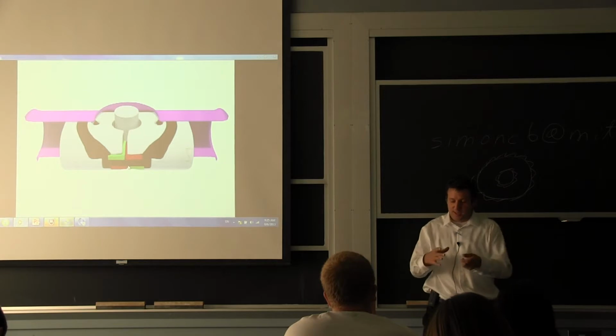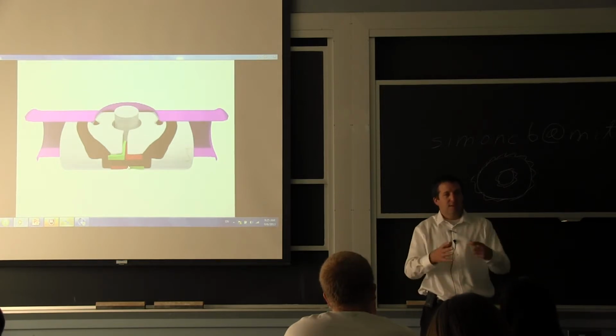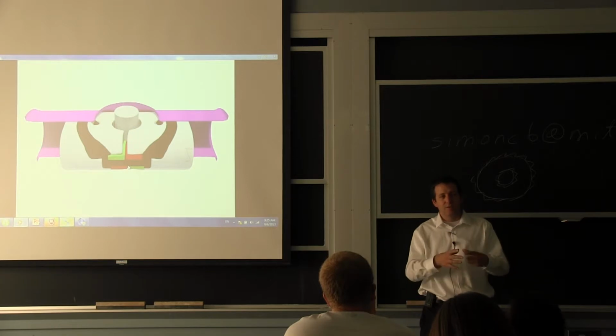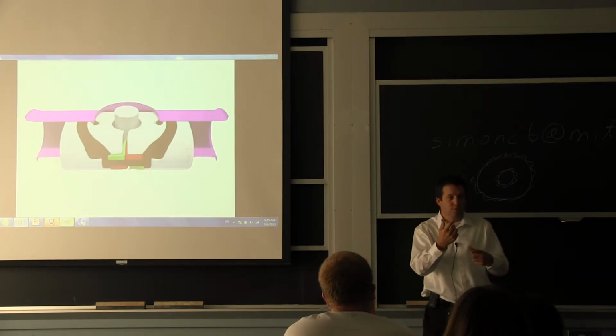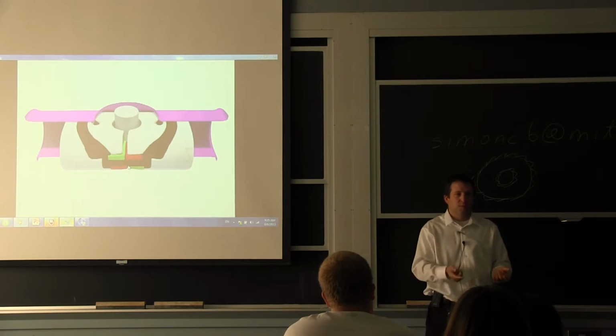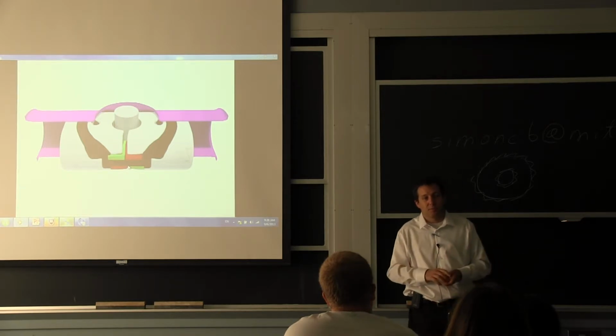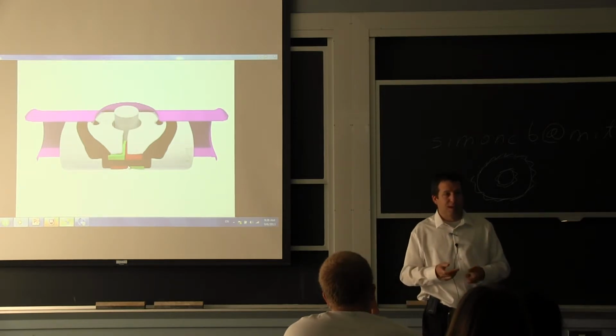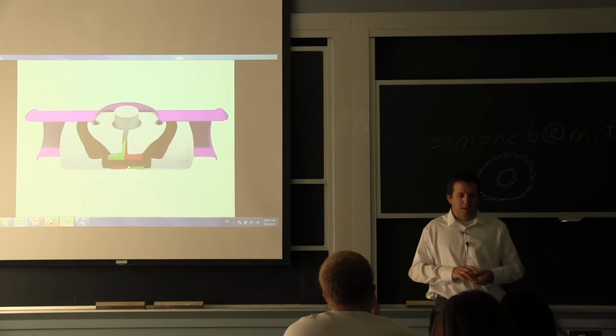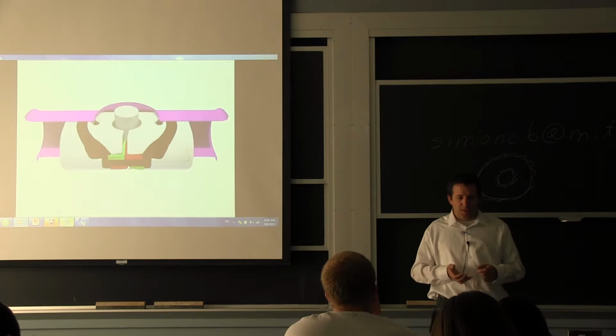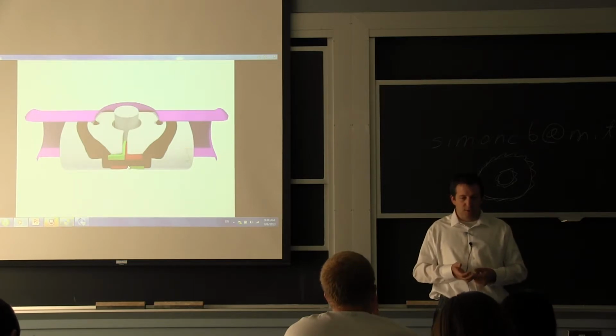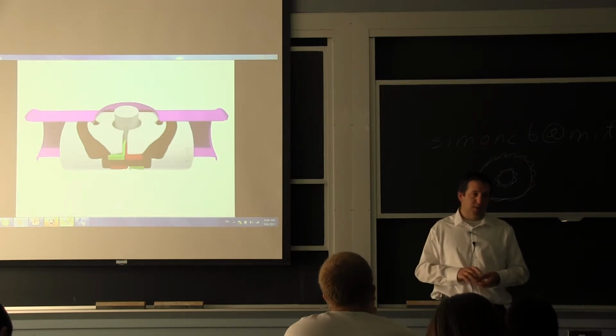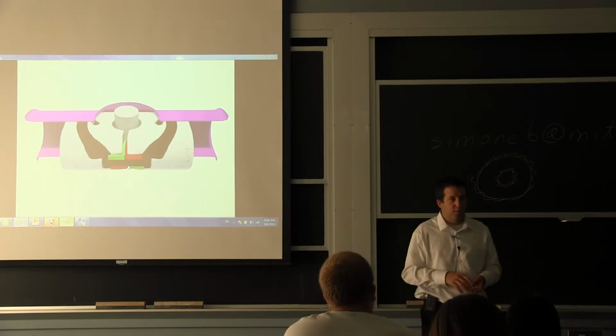When the two pieces of a little worn out rubber face each other, they need to be able to completely hold the mud. If you start having some mud going through, it's gone, because it will continue to leak in that area and you consume the whole elastomer, and that's what we see after the fact. We see a few pieces of metal left and a lot of erosion. And so again, some mechanical properties for the elastomer and mostly the environmental resistance. If there's going to be some hydrogen sulfide in the well, that's affecting the resistance and the degradation of the elastomer at high temperatures.